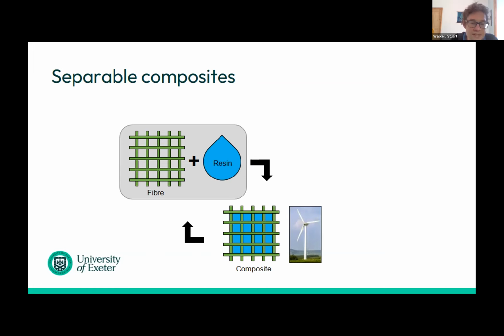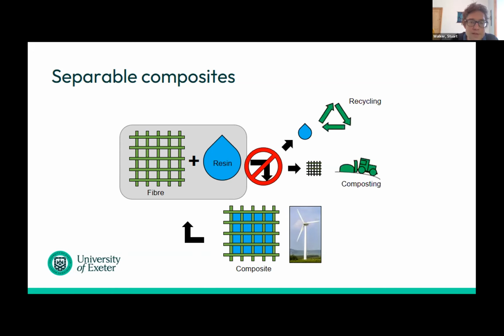The problem that we then have is that the two elements aren't as good mechanically as they were originally, so we can't actually then reuse it at the same level. We might be able to downcycle it to use it for a different material or a lower level use, or we might just be able to separate the two elements and then send them down individual recycling and composting. So if it was a bio-based material or some other kind of disposal route. So that's a route potentially to more efficient disposal.